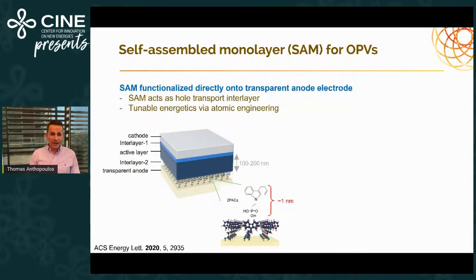So this led us to search for alternative materials. I personally spent many, many years trying to use self-assembled monolayers as surface energy modifiers, either to enable the processing of certain materials, essentially increasing or decreasing the surface energetics, or to improve injection. But that injection improvement was always focused on transistor applications. Here we came across this 2PACz self-assembled monolayer, a carbazole-based self-assembled monolayer that was a magic material and gave a very nice perovskite cell.